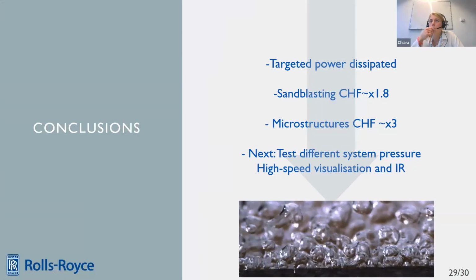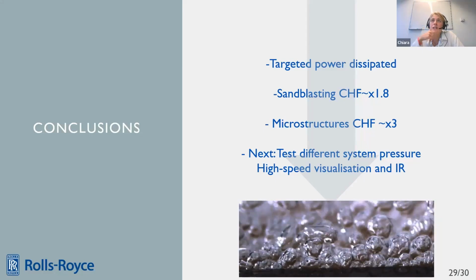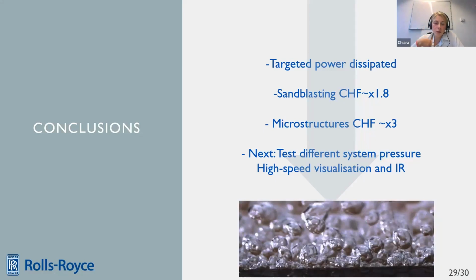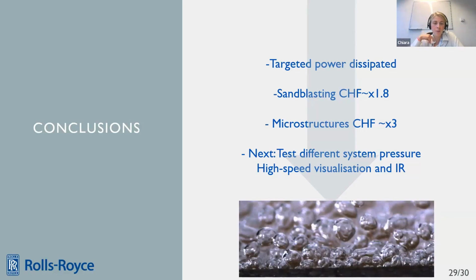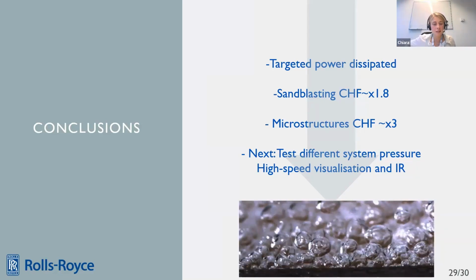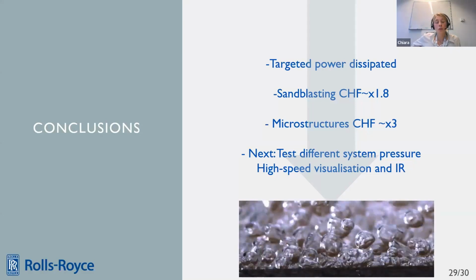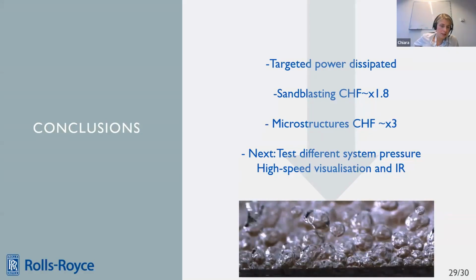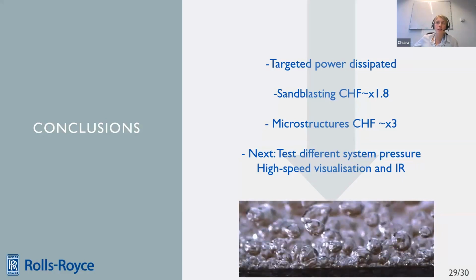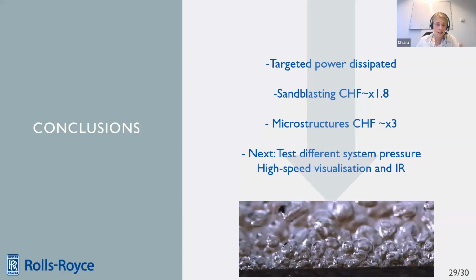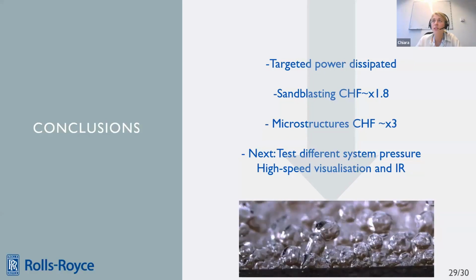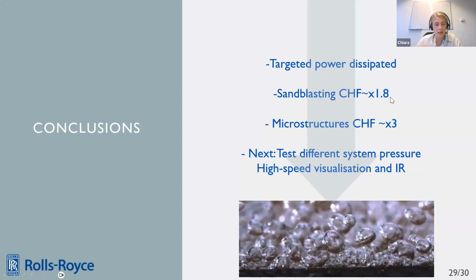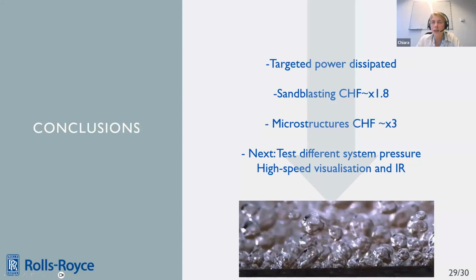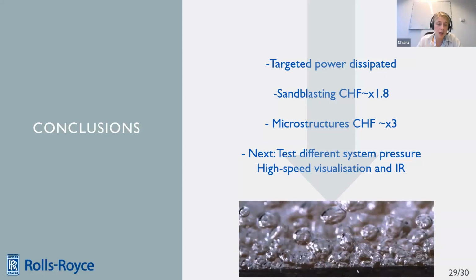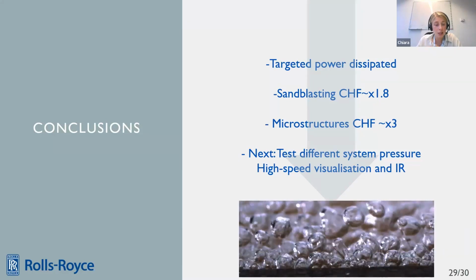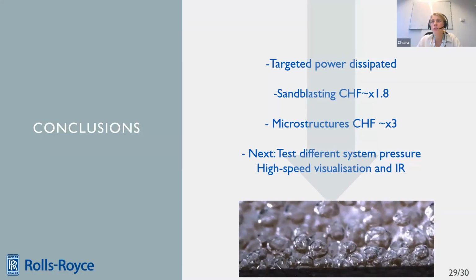So as I showed you, with two-phase flow we were able to dissipate the targeted power. We observed improvements in the critical heat flux limit using sandblasting to enhance the surface roughness. We observed almost a 2 times increase of the critical heat flux limit, and this went even up to 3 times when machining microstructures on the boiling surfaces.